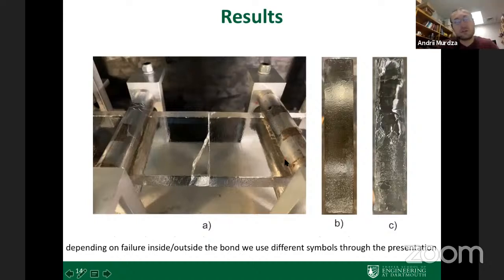So it's important to mention the types of failures we're getting. In those freshwater ice bonds, as I showed earlier, the failure would always occur outside of the bond. In the case of saline bonds, the failure would, in most cases, go right along the bond, and on image B, you can see how it looks. However, sometimes the failure would still initiate along the bond, but then slightly deviate, as you can see on image A.